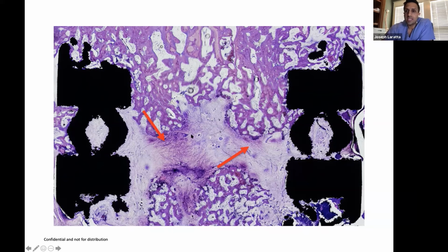So what we see here is in the center of the cage, we see this enchondral ossification. But if you look on the cage itself, so on the surface of these trabecular pores, you could see this dark purple deposition. That's immature woven bone. There's intramembranous bone formation, so bone that's forming without a cartilaginous precursor. And that's really interesting, right? So we have two types of bone formation that we're seeing that's stimulated just by the metal and the surface itself.